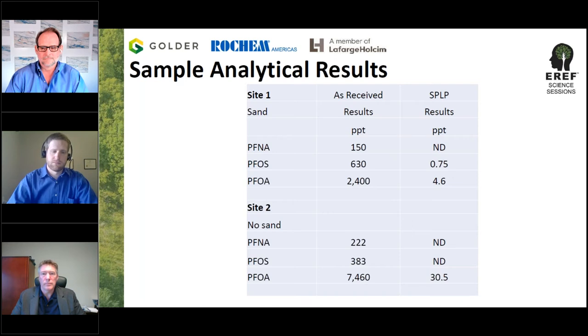But we have been able to get even the PFOA in other mixes, as you can see in the one ahead on top with the sand. We can even meet the drinking water standard for PFOA, which is 8 parts per trillion. I'm using Michigan's drinking water standards for that comparison, is that right?